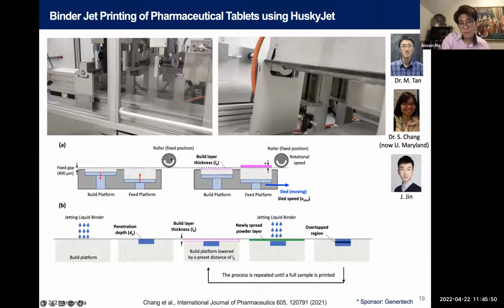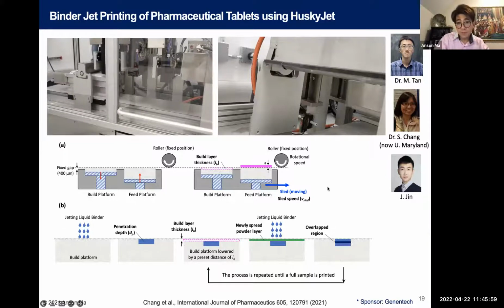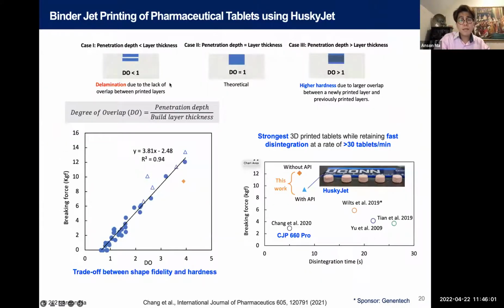And then we have some process parameters that we can control, and we can make the parts, 3D parts. We use it for making pharmaceutical tablets again. Because now we built our machine, we have full control in terms of the process parameters. One important parameter that you want to consider is, let's say you have the powder, you jet down some ink, how much binder is penetrating in the powder bed.